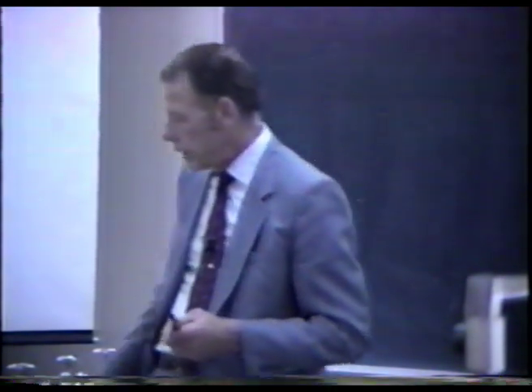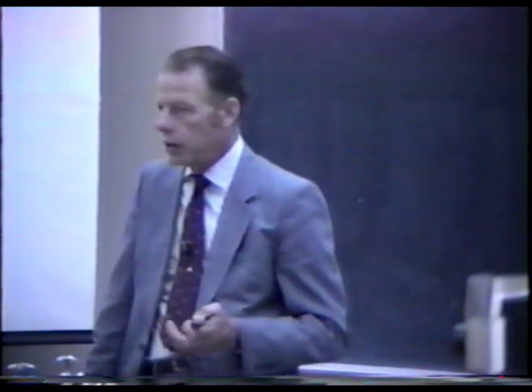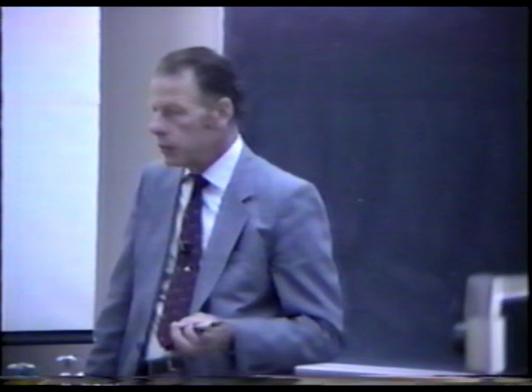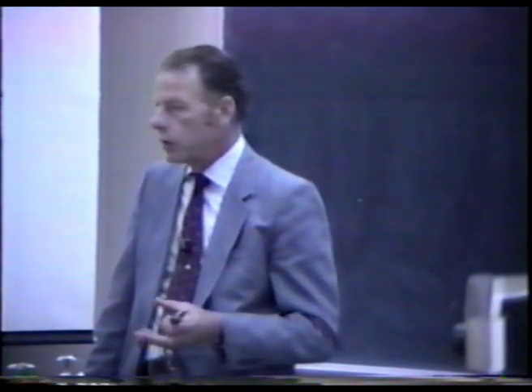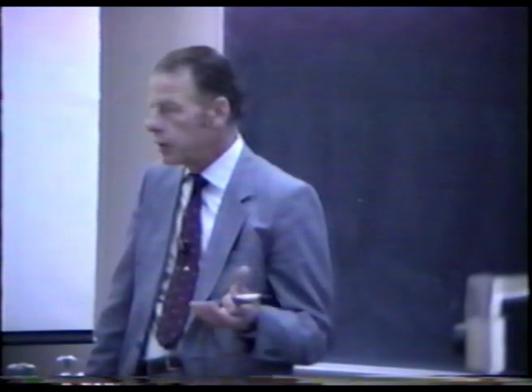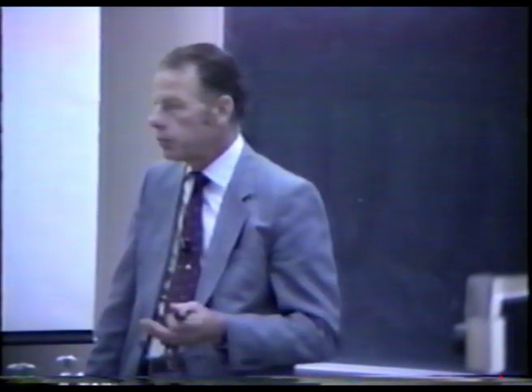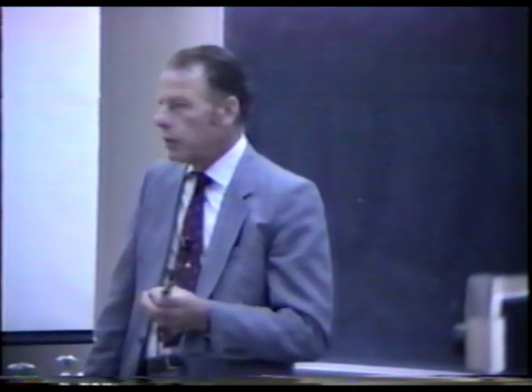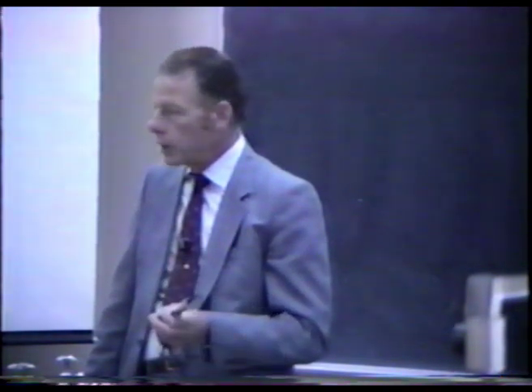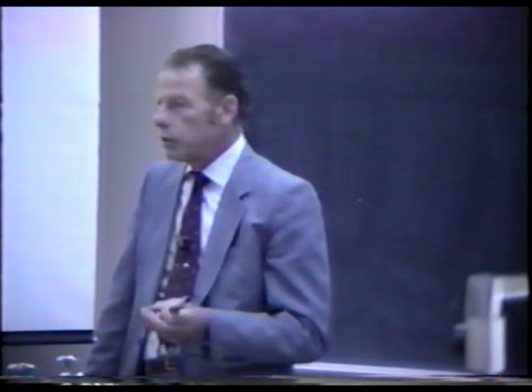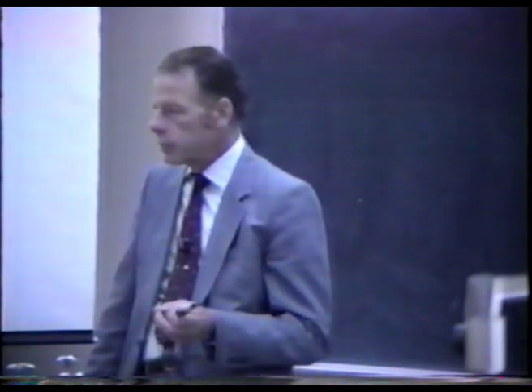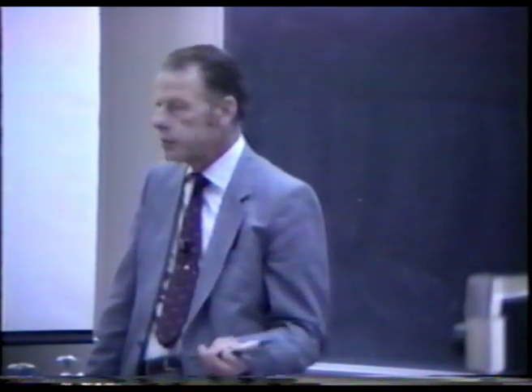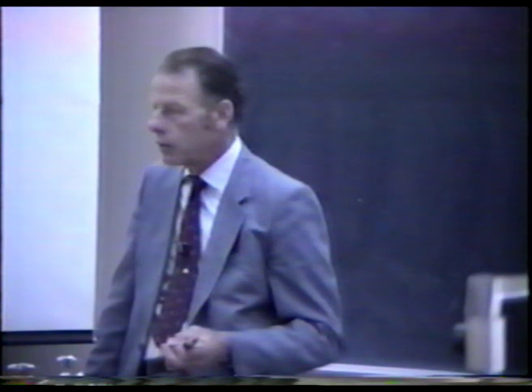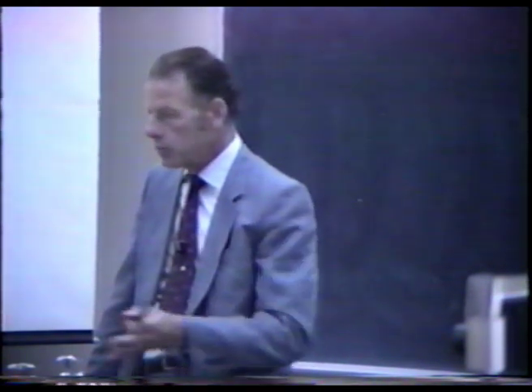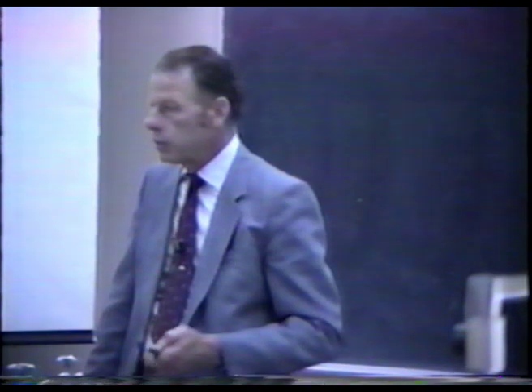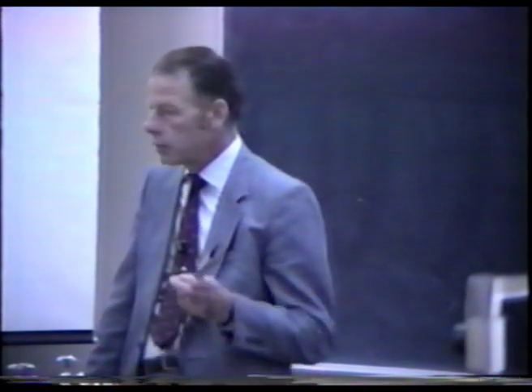Well, we actually had, after the experiment, we sent some samples to Rockwell, and they analyzed the original palladium rod that we started with. Within their detection limit, which is pretty good, they're experts on helium detection, they did not see any measurable amounts of helium in our palladium rod. And assuming their limit was the amount that was there, the most helium we could have ever gotten out of that palladium rod would have been 10 to the 12th atoms. That might explain one low-level helium sample, and that's all it could have explained. And this was over many, many days and many, many samples. So the amount of helium in the rod was barely enough to explain one low-level helium result.